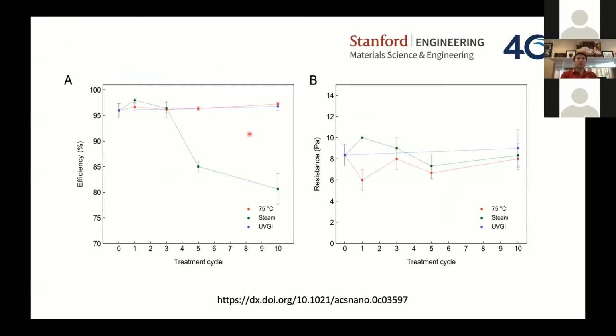But now let's look into the detail of dry heat and steam a little bit. Looking at the steam, the green curve, after 3 cycles and getting into 5 cycles, the filtration efficiency dropped too much. So using steam to treat your N95 is not recommended. You reduce the filtration efficiency by a lot. And the dry heat, this is 75 degrees Celsius, looks very good. 10 cycles, each cycle 30 minutes, looks very good.